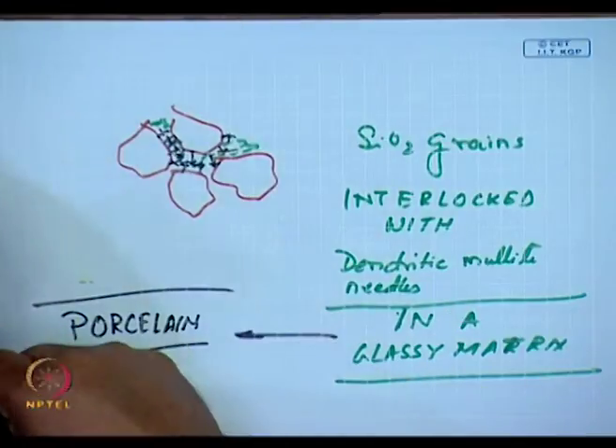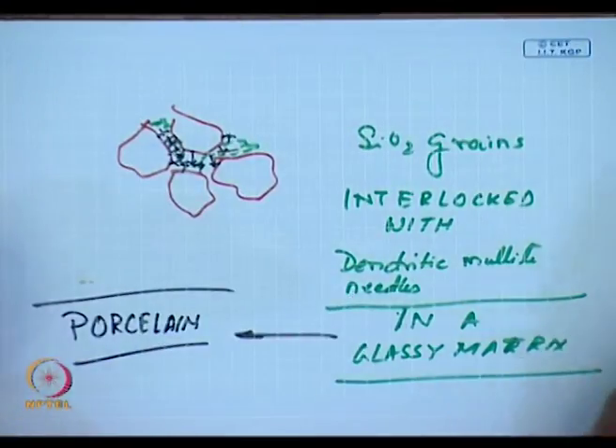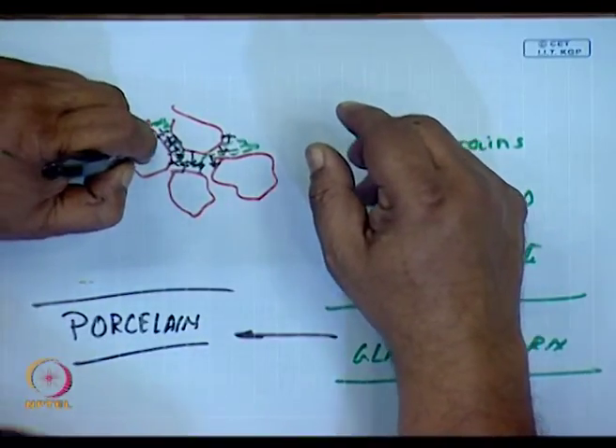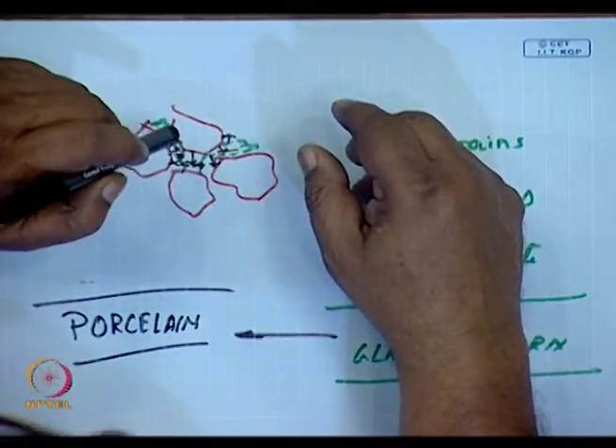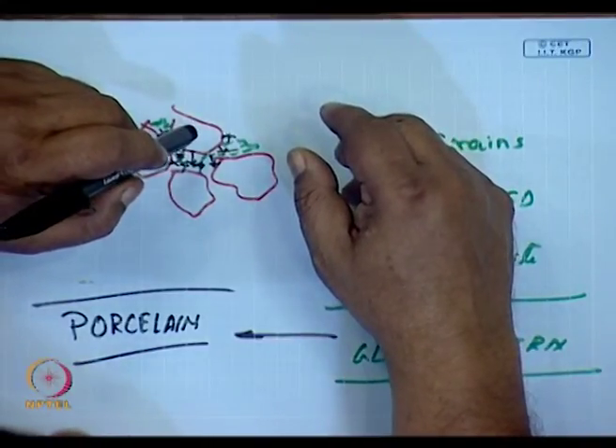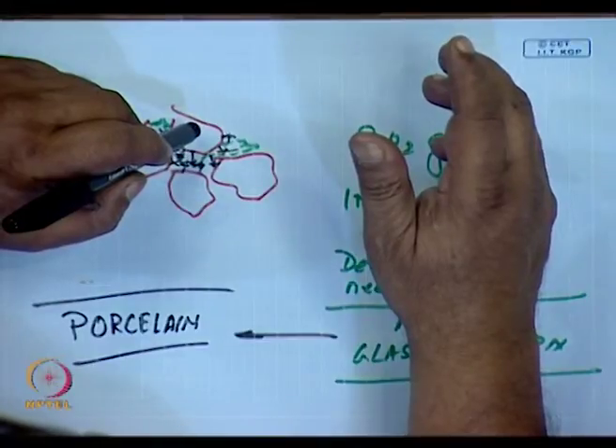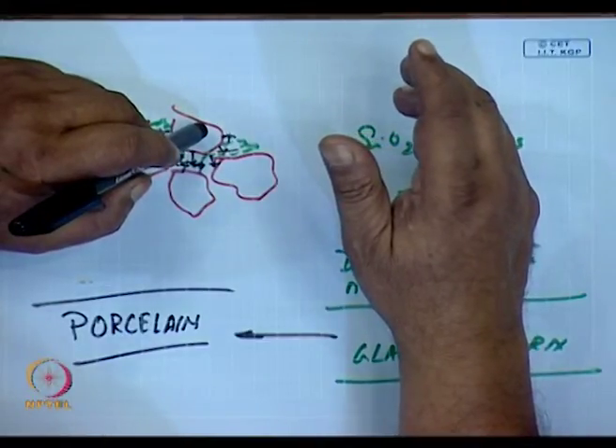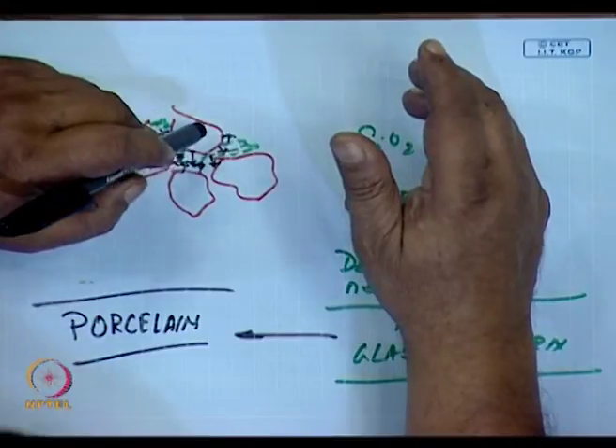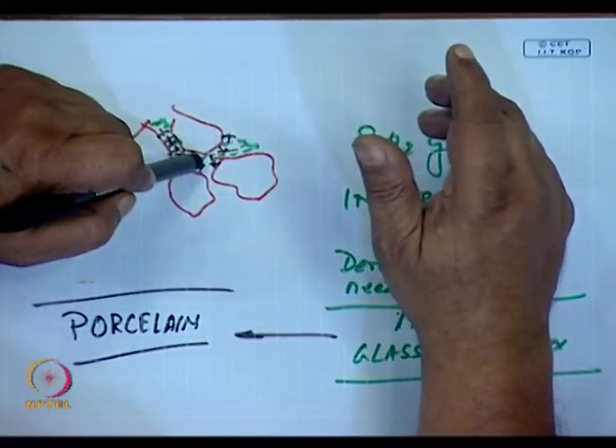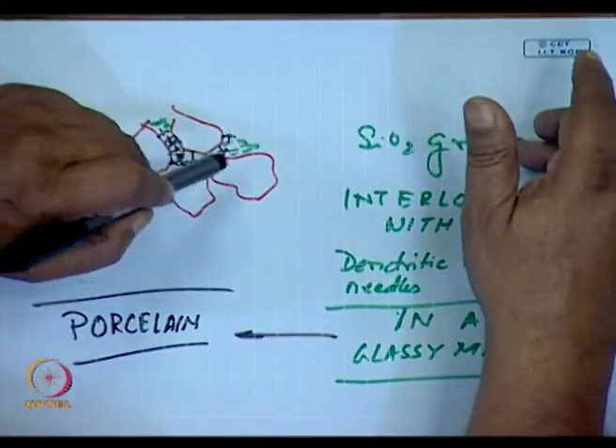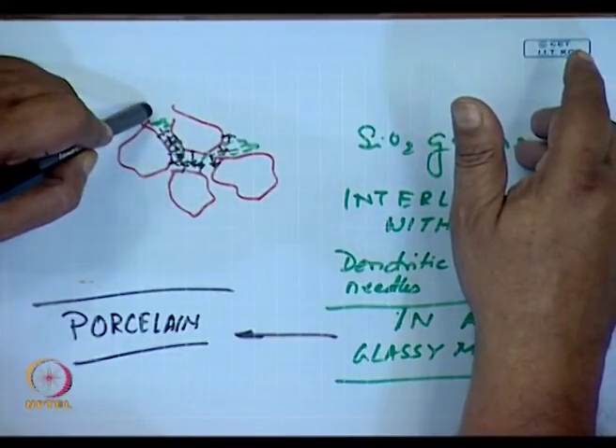But the very presence of glassy phase in industrial applications can cause a problem. Even though the silica will not melt below 1700, the mullite will also not melt below 1840, yet the material will soften at much lower temperatures due to the presence of glassy phase, which will soften at much lower temperatures.